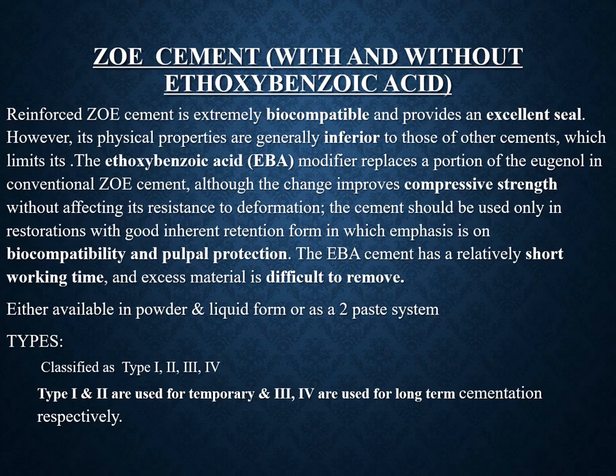Zinc oxide eugenol cement is extremely biocompatible and provides a very good seal; however, the physical properties are generally inferior to those of other cements. EBA (ethoxy benzoic acid) is a modifier which replaces a portion of eugenol in conventional zinc oxide eugenol cement and improves the compressive strength without affecting its resistance to deformation. This cement should only be used in restorations with good retention.